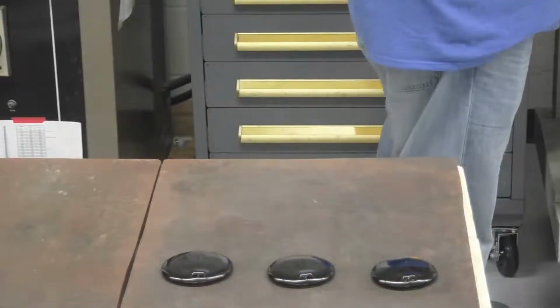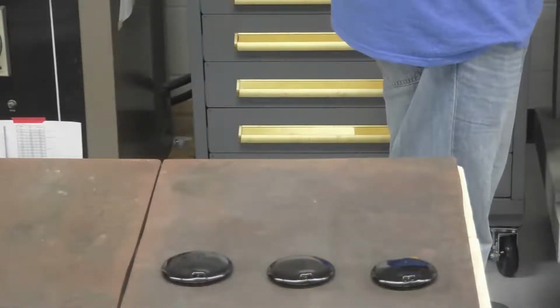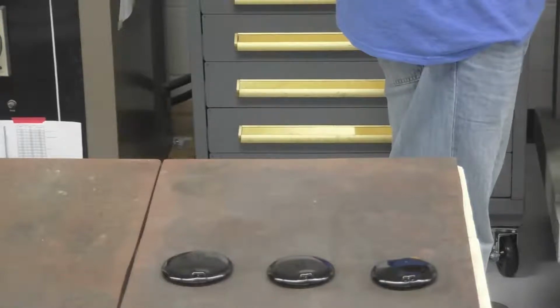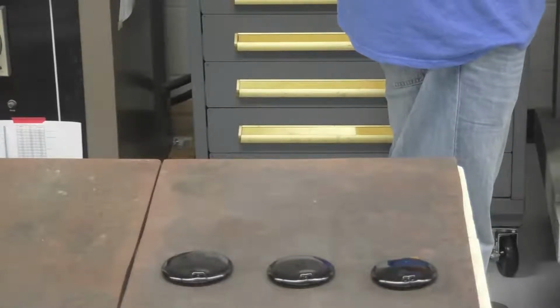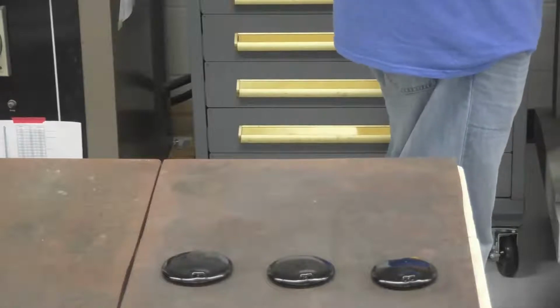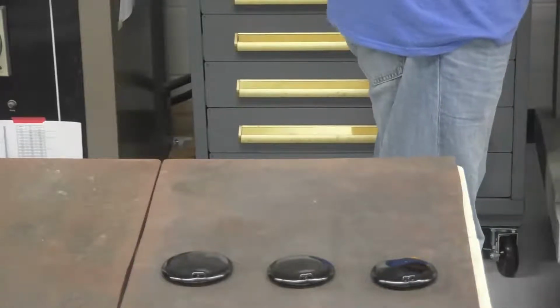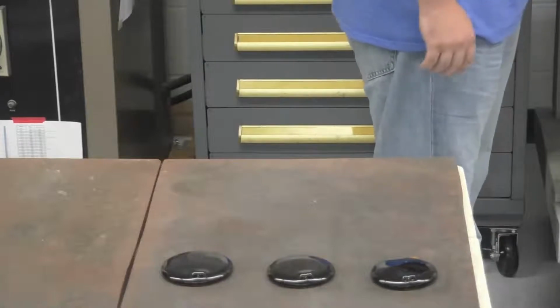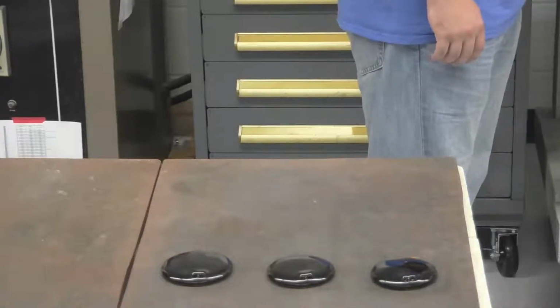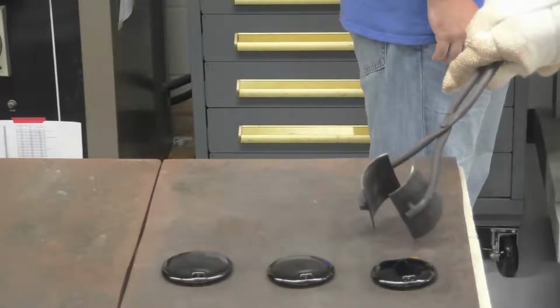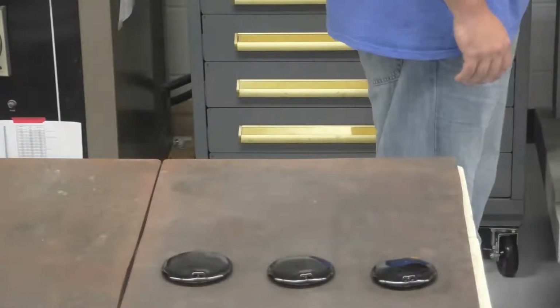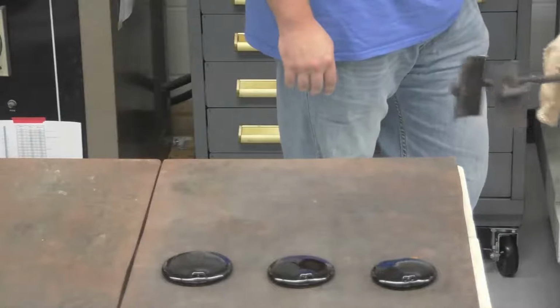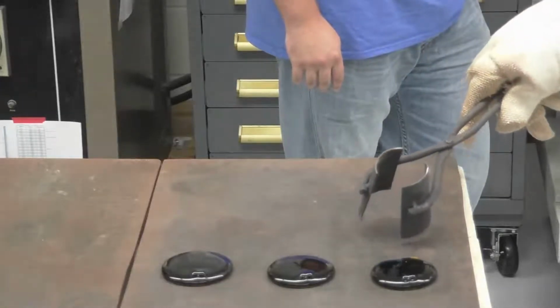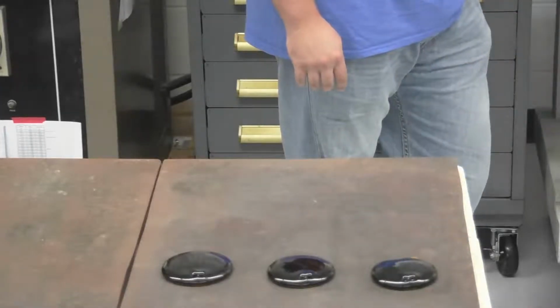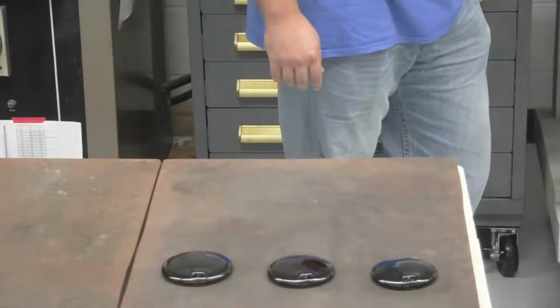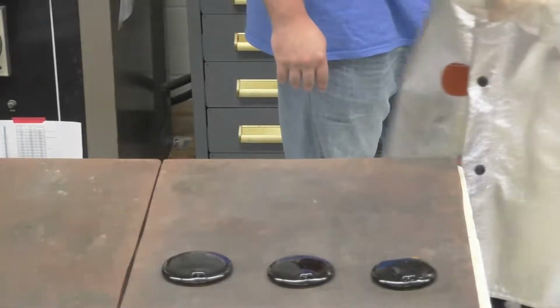This one is a little bit high on the calcium flux. So we're switching from high sodium to high calcium flux. And this one has a fairly high load of manganese, so this one will probably eventually be purple. So we'll pour that one right here. I can smell something, I guess the coating burning off of the fire-resistant glass mat there. So that's glass. Yes. So that's probably a good time to tell you what's going on there.